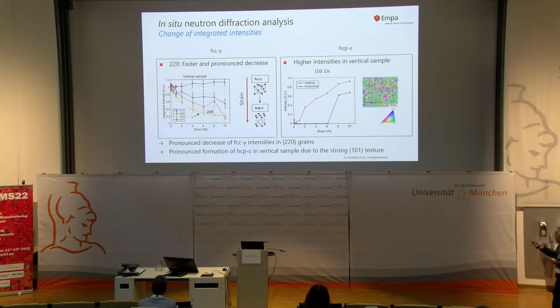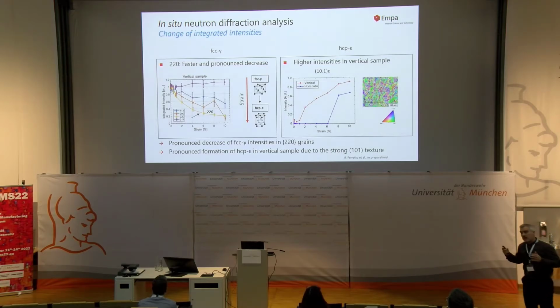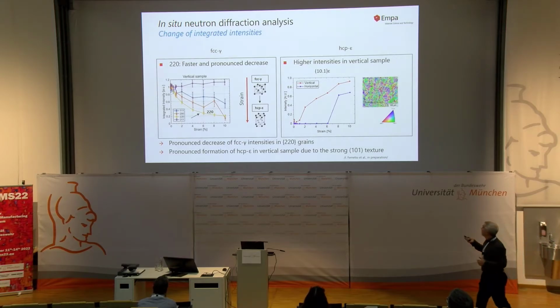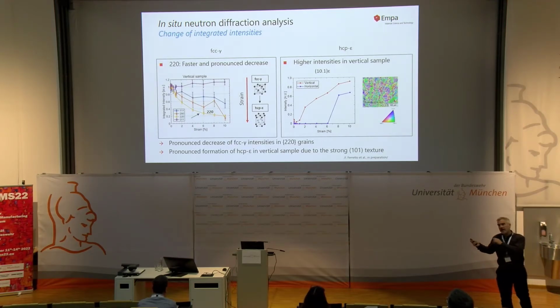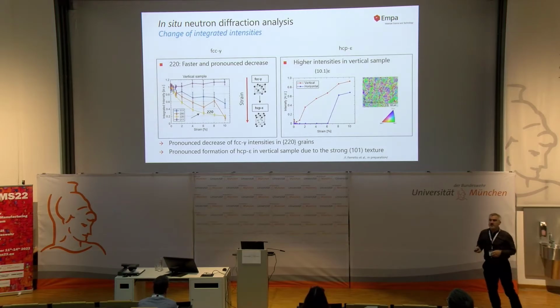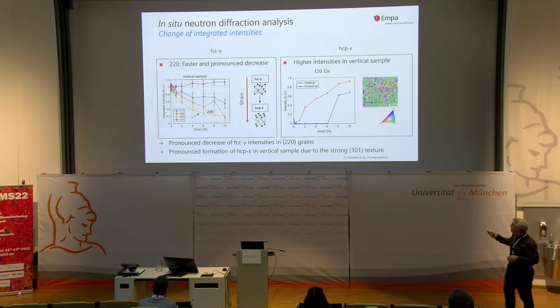Looking into our most pronounced epsilon peak as a function of the build direction, you could also see here that for the vertical direction, epsilon martensite starts to form, or we could detect it, at much lower strains than here for the horizontal. So here it's rather flat. It doesn't mean that it's not there. It's just difficult to detect because the peaks are small. But this martensite transformation seems to start at much higher stresses or much higher strains.